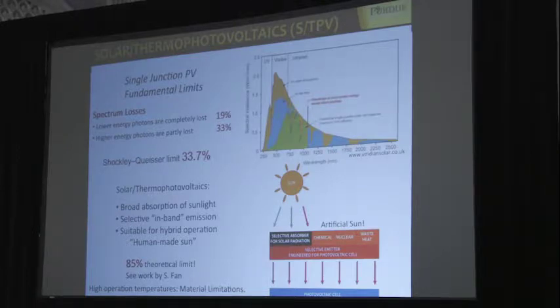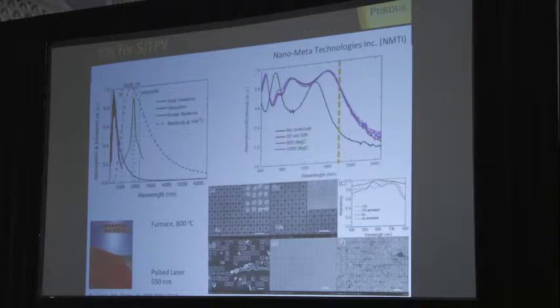The challenge is that the plasmonic material should be able to operate at temperatures like 1200 Celsius. And of course, it cannot be done with gold and silver. Having materials like titanium nitride opens up this very interesting possibility. And I'm sure in our work, we are getting close to demonstrating the prototype, but at least we already showed all key ingredients of these thermophotovoltaics.